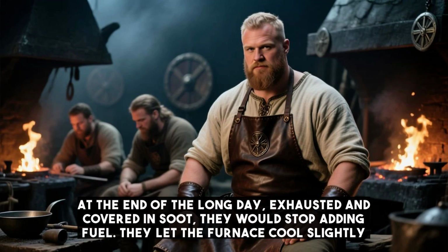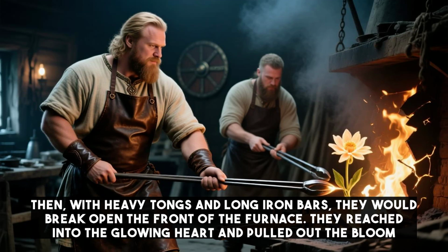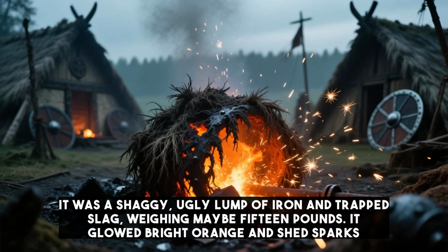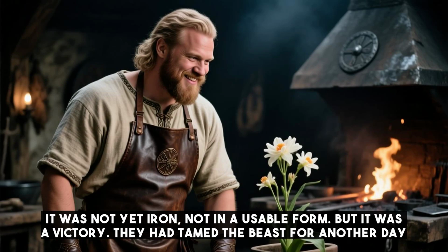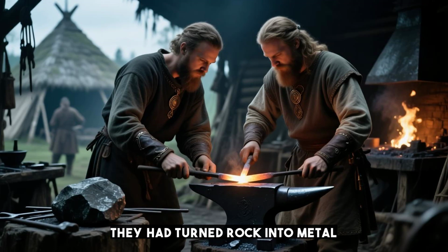At the end of the long day, exhausted and covered in soot, they would stop adding fuel. They let the furnace cool slightly. Then, with heavy tongs and long iron bars, they would break open the front of the furnace. They reached into the glowing heart and pulled out the bloom. It was a shaggy, ugly lump of iron and trapped slag weighing maybe 15 pounds. It glowed bright orange and shed sparks. It was not yet iron, not in a usable form, but it was a victory. They had tamed the beast for another day. They had turned rock into metal.